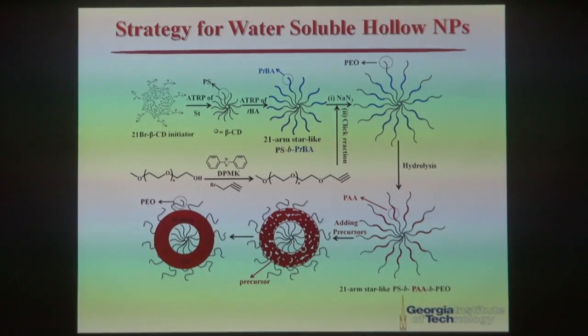Likewise, we want to make water-soluble hollow nanoparticles, again for biomedical applications. To do that, we recently designed a star-like ABC tri-block copolymer. The A block is PEO, water-soluble, biocompatible. The B block is poly(tert-butyl acrylate) in blue, hydrophobic. The C block is polystyrene in black, the innermost block. Again, this combines two-step atom transfer radical polymerization with a one-step click reaction.